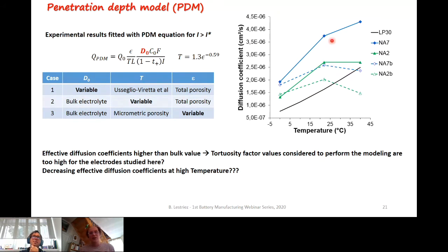But if you look at the values, they are to some extent too high compared to the bulk value. For example, for Na7, the extracted diffusion coefficient is 3 times higher than the bulk value, which is difficult to conceptualize. We would have expected rather to find lower diffusion coefficients from the fit compared to the bulk value, because we expected that some additional limitations we don't know, such as interfacial effects or others, would have resulted in a decrease of the diffusion coefficient. And also what you can see is that the extracted values all depend on the electrode formulation. So this invited us to look at things differently.